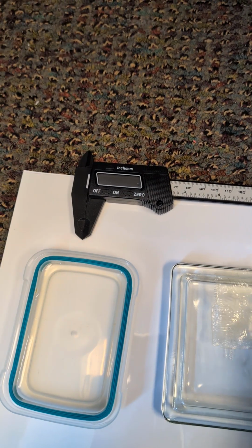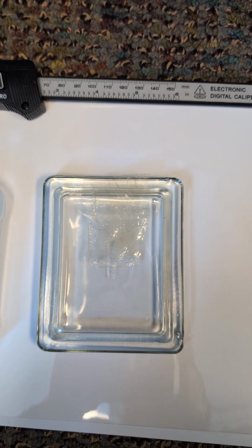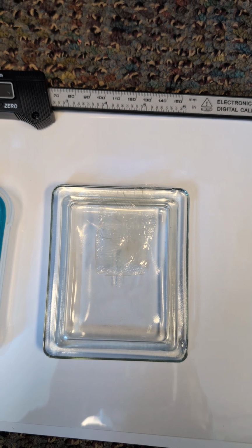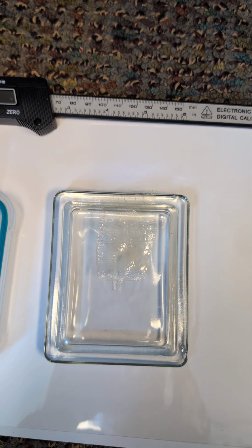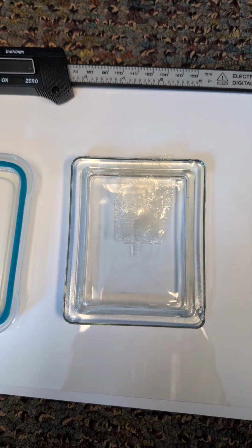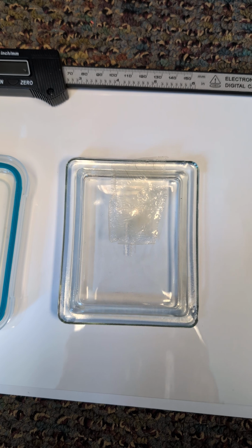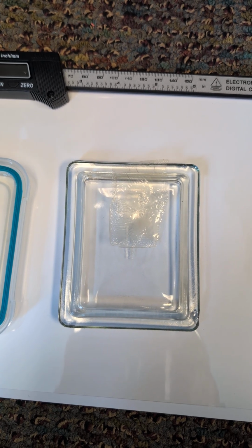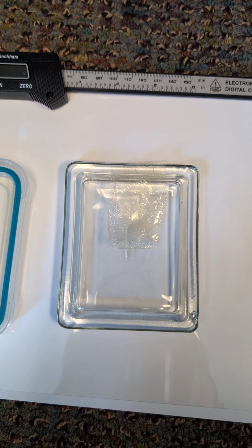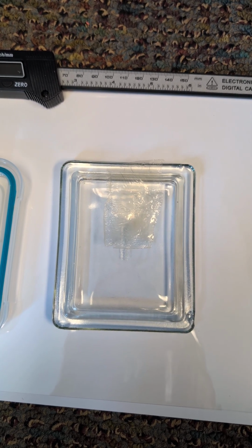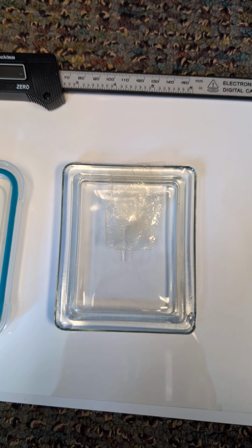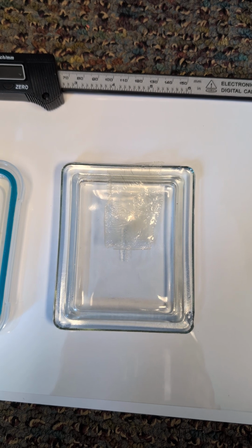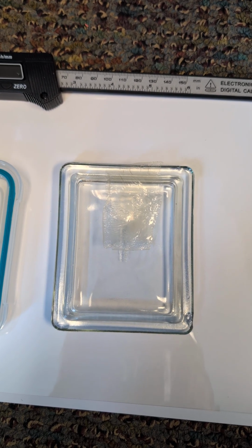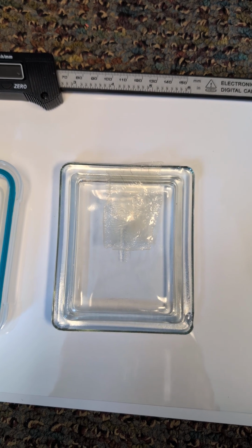Filter to remove any undissolved chitosan. And then that is dried at 60 to 70 degrees Celsius for 4 to 5 hours. Upon cooling to room temperature, I then place it in a 20% aqueous potassium hydroxide bath, and that's very important to follow this sequence of events. That will remove residual acetic acid, and then after that immersion, I remove it and wash it with distilled water very thoroughly and place it out to dry to constant mass at room temperature.